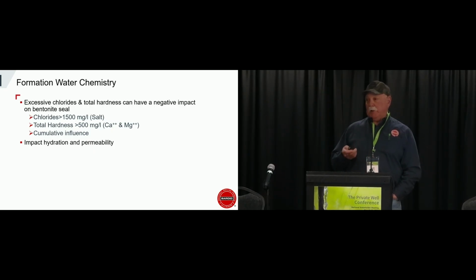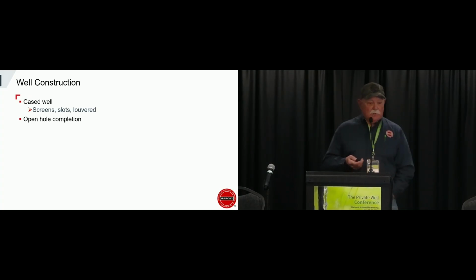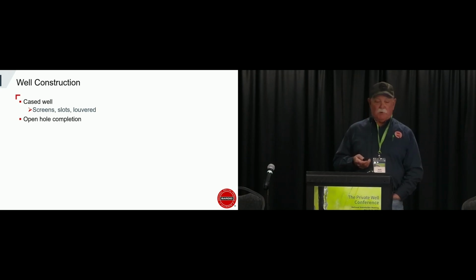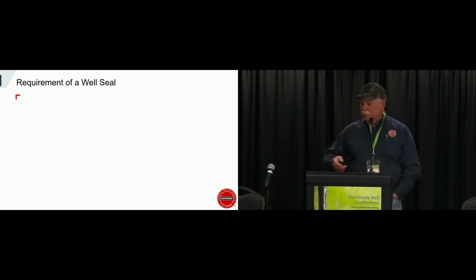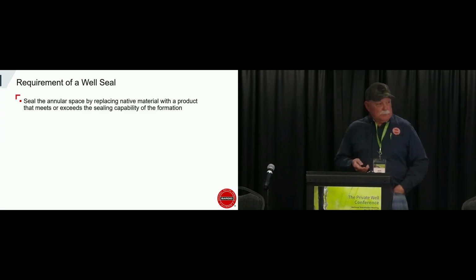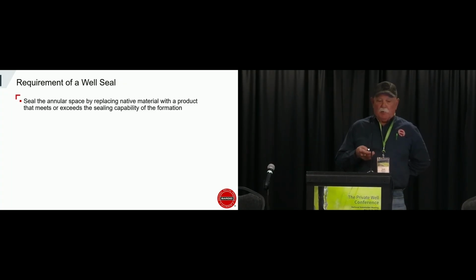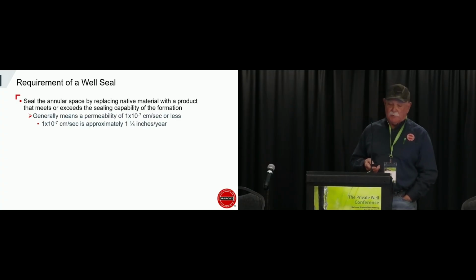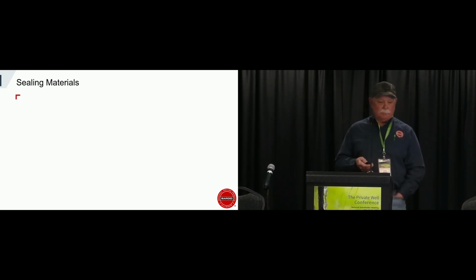If your bentonite's not able to hydrate, it's contaminated. That will have an impact on hydration of the product and also the permeability, which won't make a good seal. So well construction, we have cased wells, we have screens, we have slots, louvered, and also open hole construction. So basically the requirement of the seal is to seal the annular space between the casing and the borehole by replacing the native material with a product that meets or exceeds the sealing capacity of the formation. And just generally that means a permeability of 1.0 times 10 to the minus 7 centimeters per second, or approximately 1.25 inches per year. Pretty low.